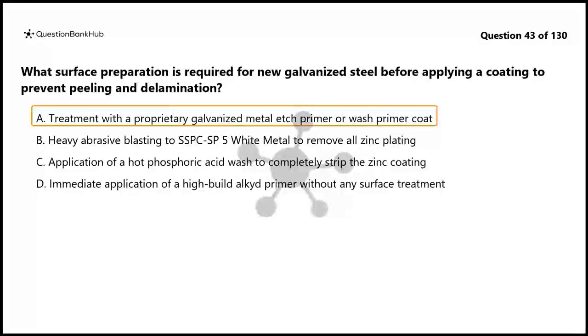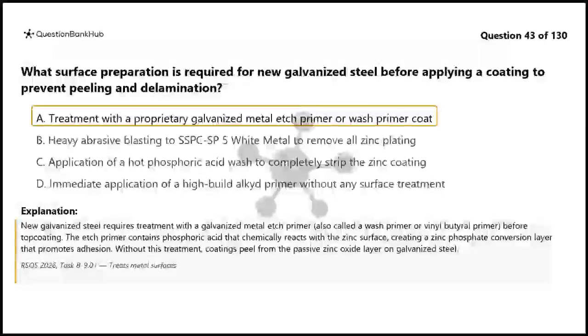The correct answer is A. New galvanized steel requires treatment with a galvanized metal etch primer, also called a wash primer or vinyl butyral primer, before top coating. The etch primer contains phosphoric acid that chemically reacts with the zinc surface, creating a zinc phosphate conversion layer that promotes adhesion. Without this treatment, coatings peel from the passive zinc oxide layer on galvanized steel.